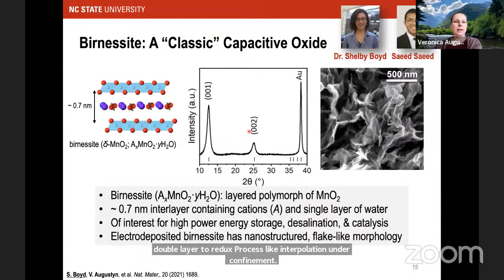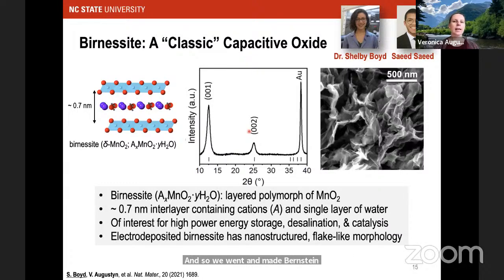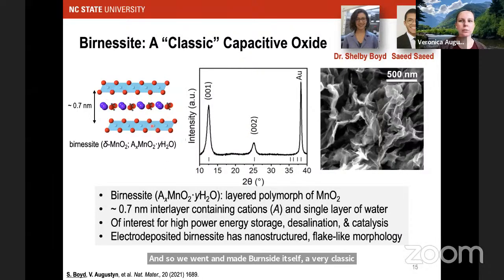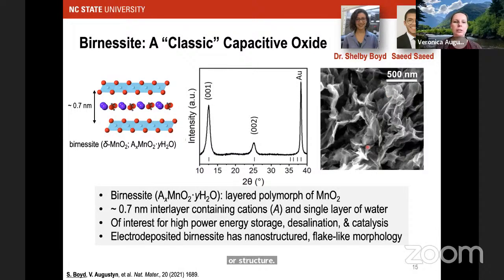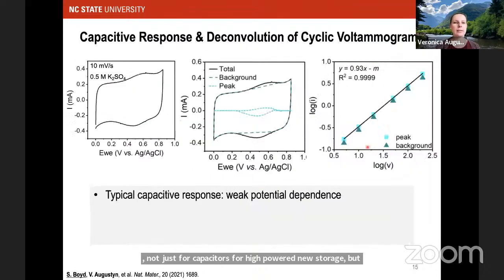And so we went and made birnessite itself, a very classic capacitive oxide. This is the structure of that material. This is the X-ray diffraction pattern showing its very nice layered structure. This is that electrodeposited film that I mentioned earlier. It's a material that's of interest not just for capacitors, for high power energy storage, but also desalination, as well as catalysis. When we talk about the capacitive response, that weak potential dependence, this is just showing you that it looks very similar to the micron scale electrochemically derived material that I just mentioned.